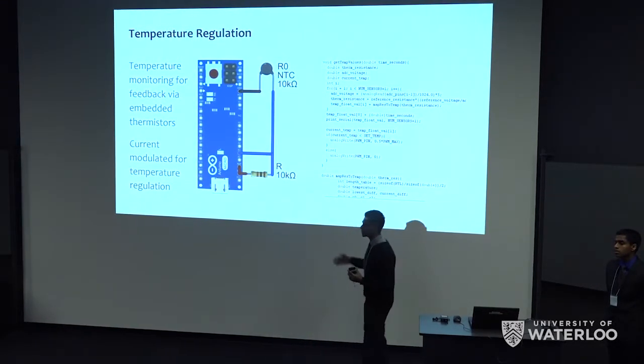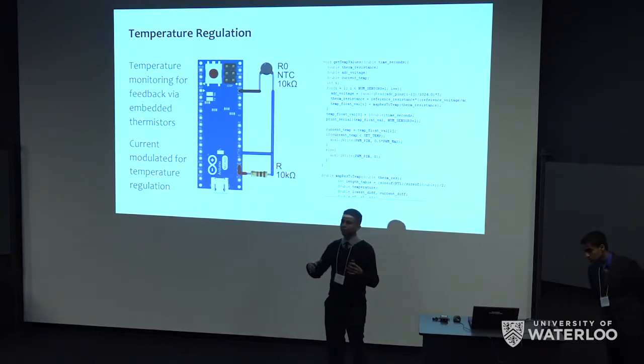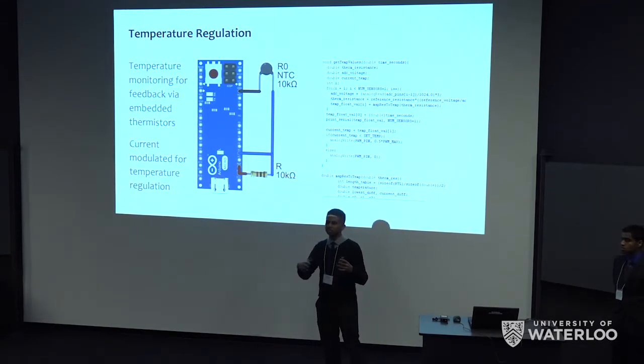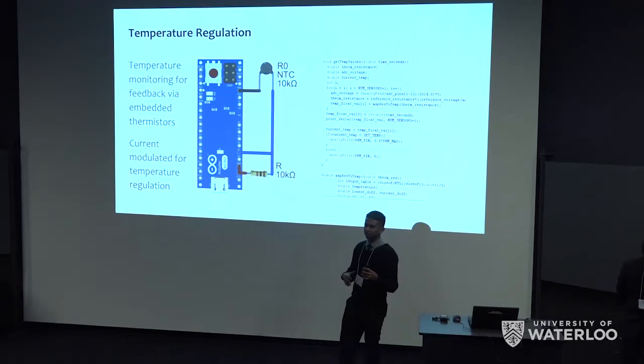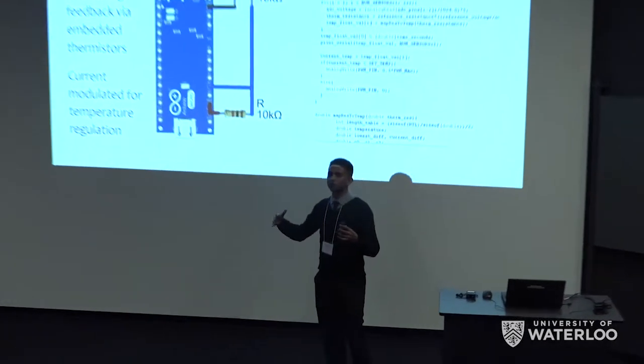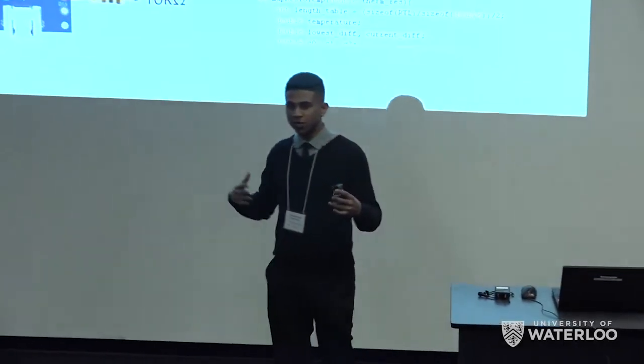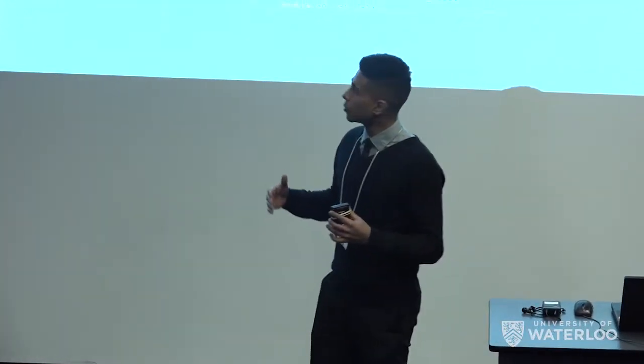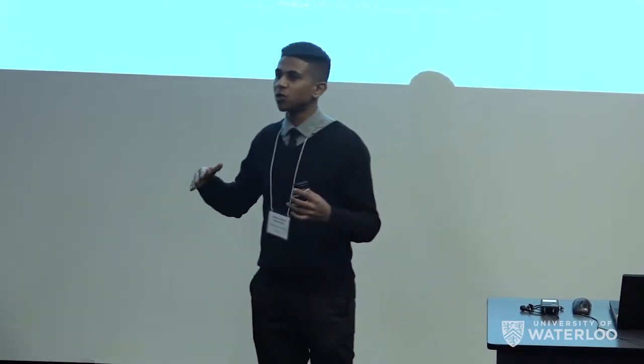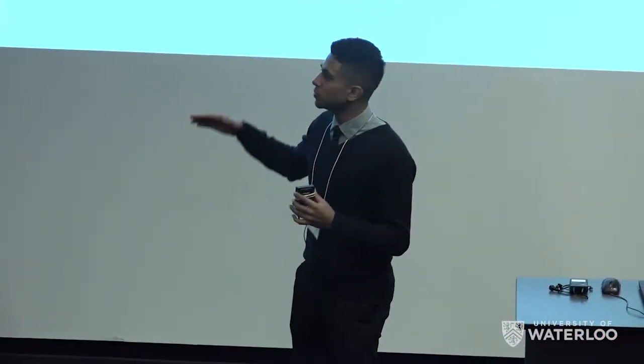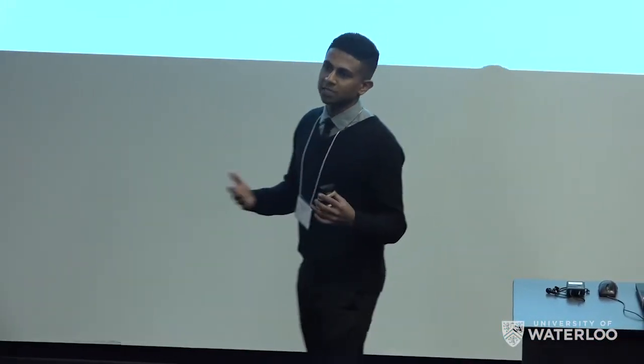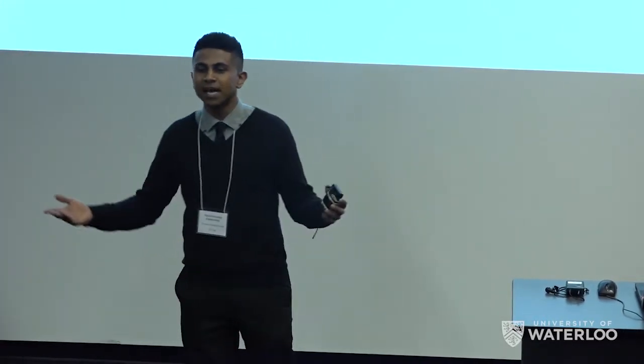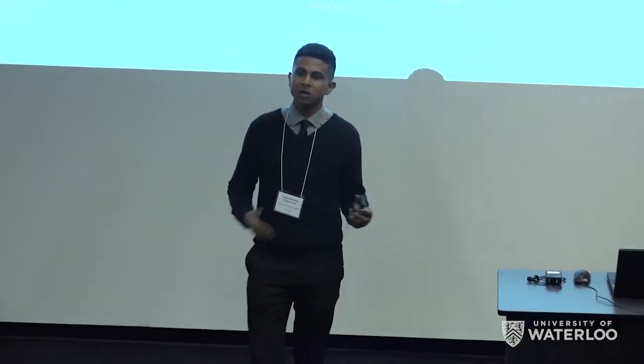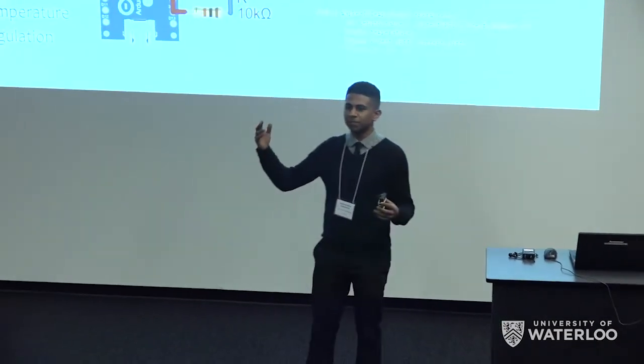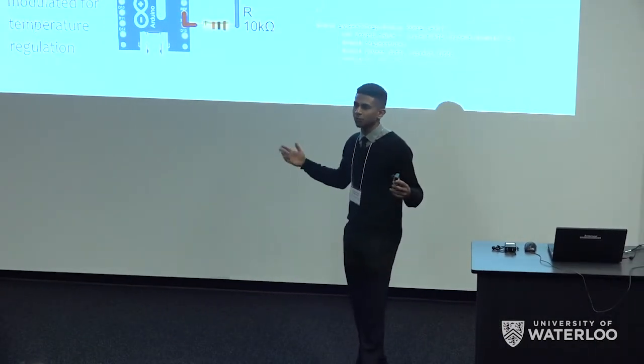And so we have these thermistors embedded within the material to gain an accurate representation of what the distribution of temperature is inside the material. And this allows us to create a feedback system where we're not only monitoring, but regulating the temperature as well. So what we do is we measure the temperature within the material and then decide with the microcontroller how much current to supply to maintain a set temperature. So for example, if a customer believes that 29 degrees Celsius is what they deem comfortable, we can ramp up until we hit that set temperature and just maintain it for the remainder of their usage.